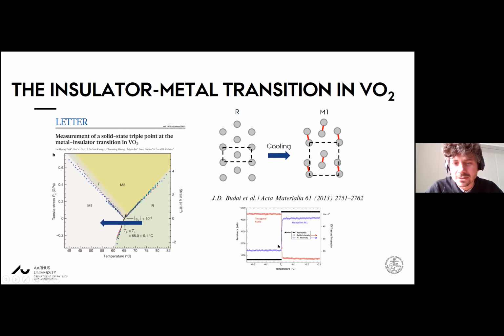And here is a nice plot of the simultaneous nature of these transitions, where we have diffraction and resistance measured simultaneously in the bottom right-hand corner. And we see that within less than 0.001 Kelvin, these transitions occur together. And the very sharp nature of this transition indicates that it's a first order phase transition. Okay, so we're going to investigate the reverse process, which is using light to drive from the dimerized state to the rutile phase. And I'm going to tell you about how we've been working towards watching how this happens and investigating whether vibrational coherence can play any role.